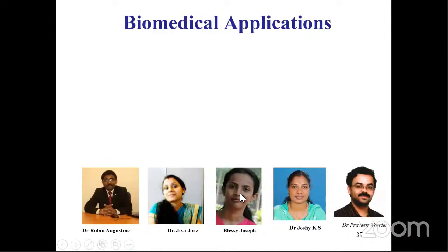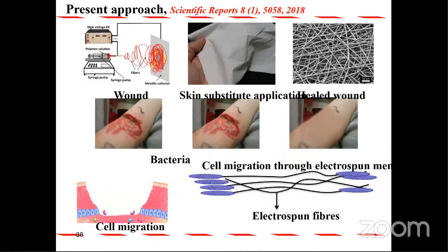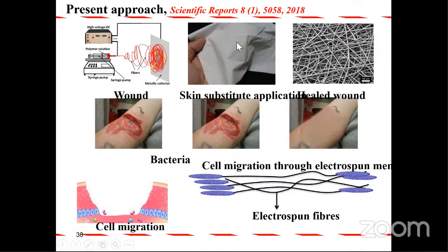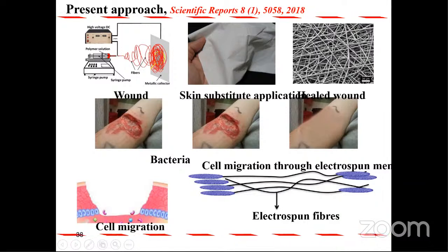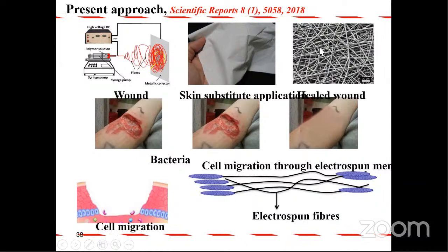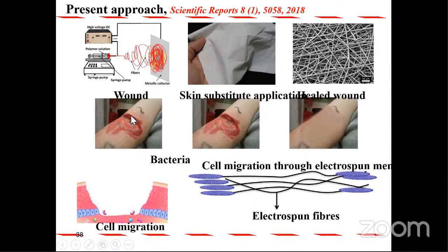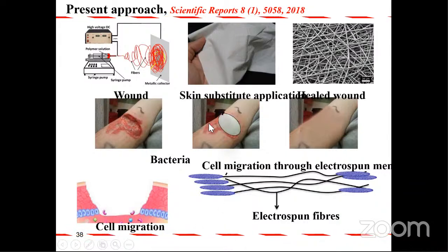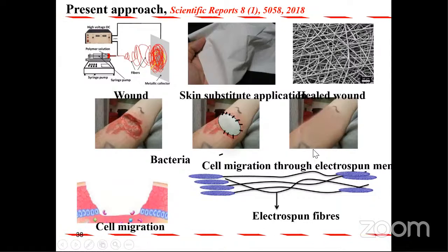Let me show you some of our biomedical applications. My group is very active in biomedical applications. You can see my co-workers, postdocs. We do a lot of electrospinning, PCL, PLA, polymer blends, and we make non-woven scaffolding material. You see? If you examine this under electron microscope, we get a beautiful nanostructure. Then we made wounds, sacrificial wounds. The wound has been closed by this tape. You see, after a couple of weeks, complete healing of the wound.